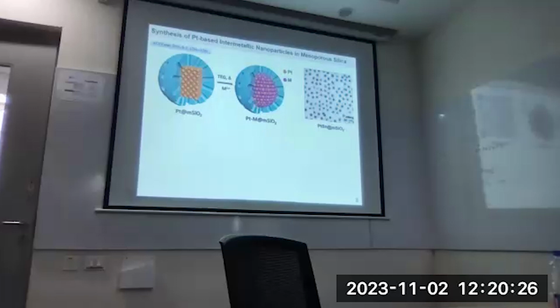So for me, I used to make these platinum-based nanoparticles and then make them as platinum tin. This metal could be either tin, lead, or even zinc. And we could use them for various reactions, right? So you can see these are stable at least until 800 degrees Celsius. So I have this porous silica shell, and inside I have my metal nanoparticle, the intermetallic nanoparticle, which is platinum and tin.